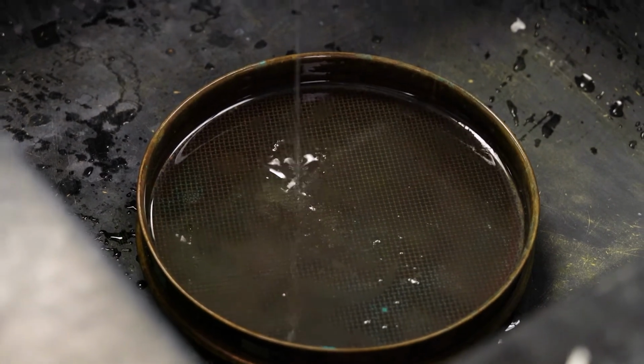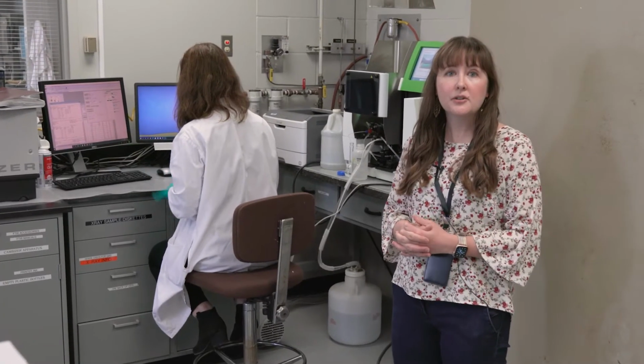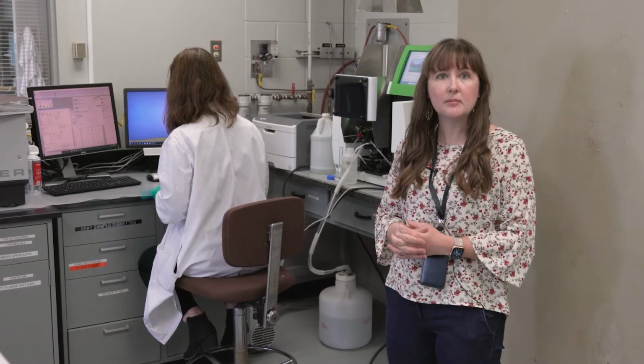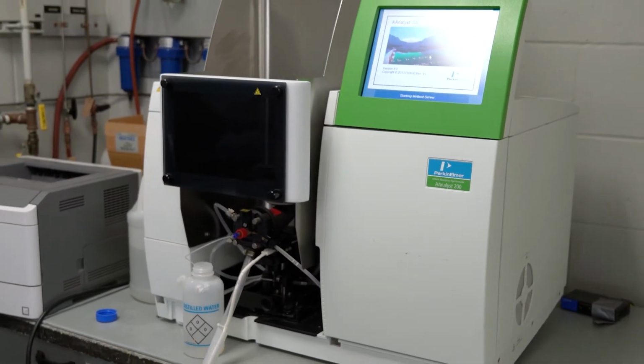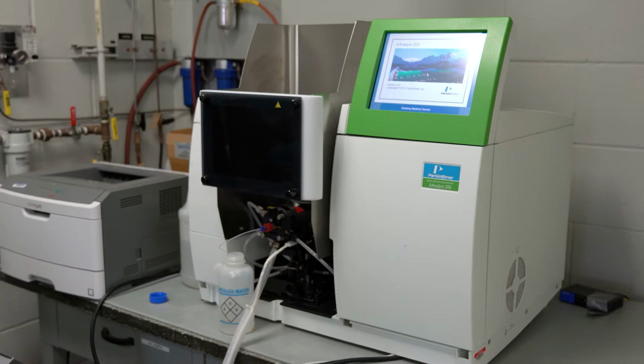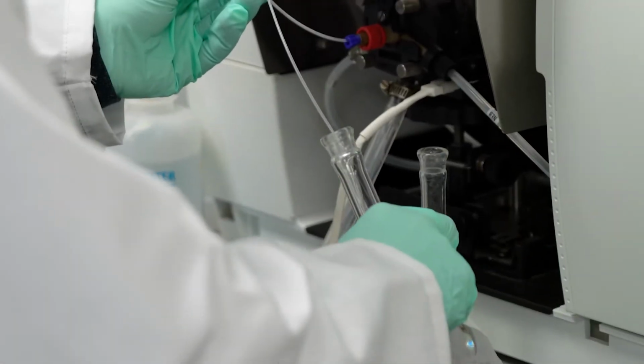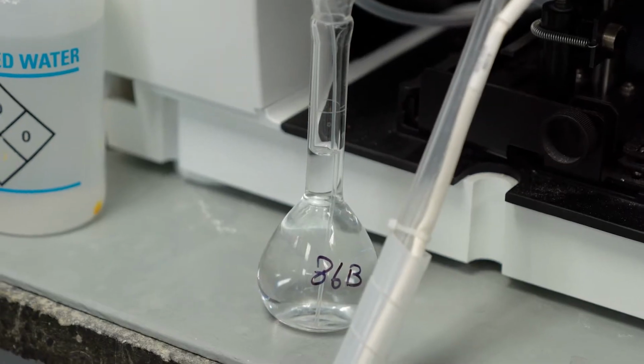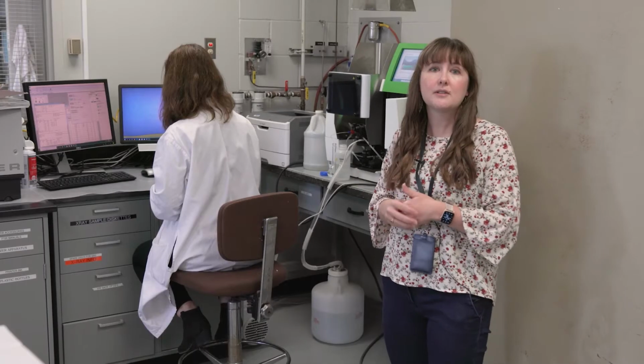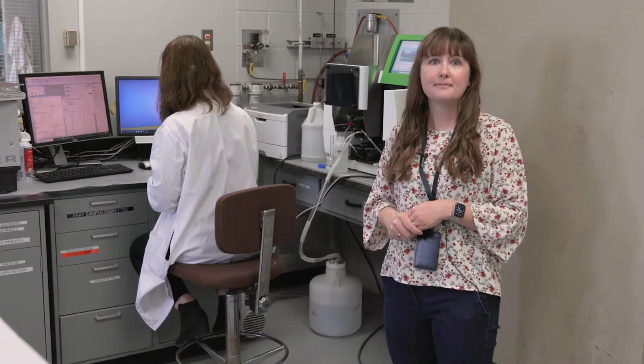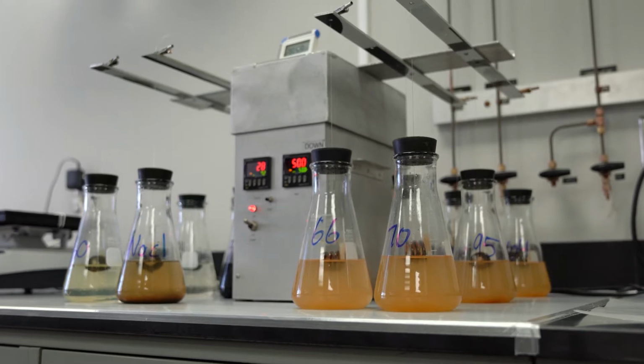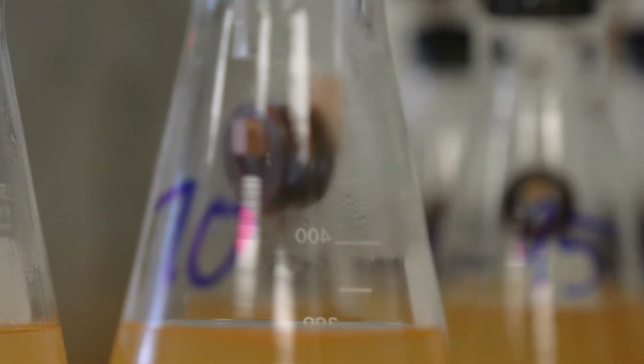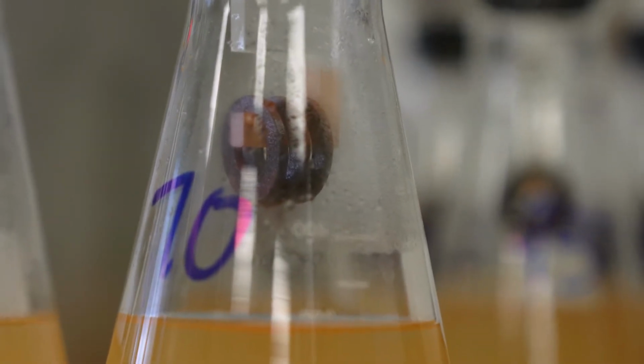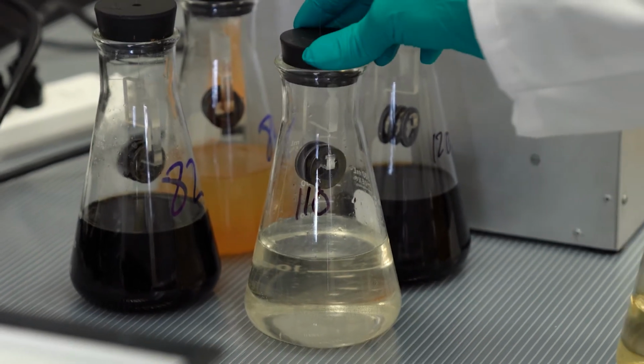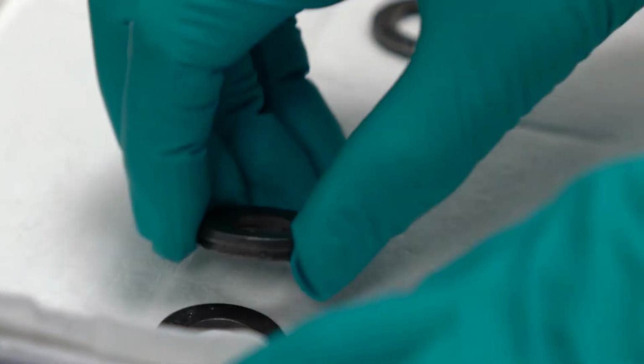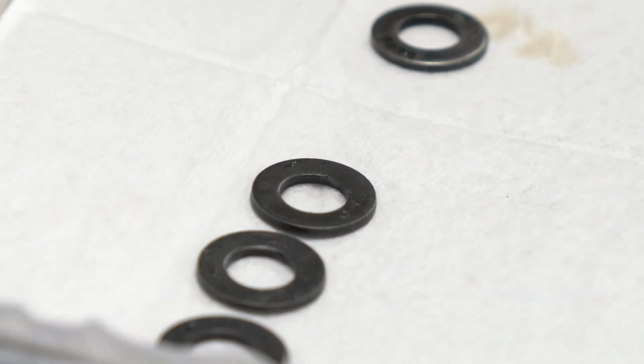Okay, we test the active ingredient in our de-icers, which is magnesium chloride, and we use the atomic absorption spectrometer to measure that. We make a solution, the instrument sucks up the solution, and there's a detector in there that gives us a concentration. We do a corrosion test on our de-icer samples to determine how corrosive the de-icer is for steel, and we use steel washers dipped in the de-icer over a 72-hour period.